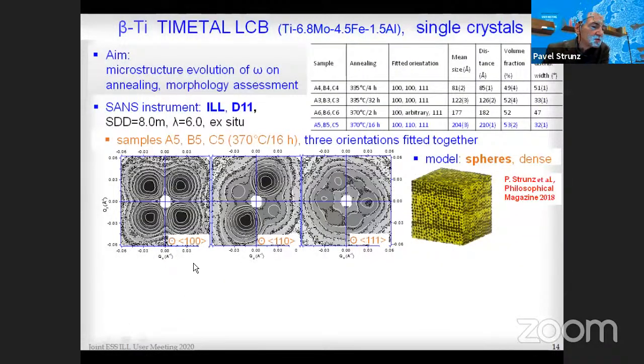When talking about precipitates, the best technique to use is small angle neutron scattering. I show here some data measured at ILL at D11. This data are from Timetal LCB single crystals. The aim of this research was to determine the microstructure of omega after annealing, particularly to determine morphology.